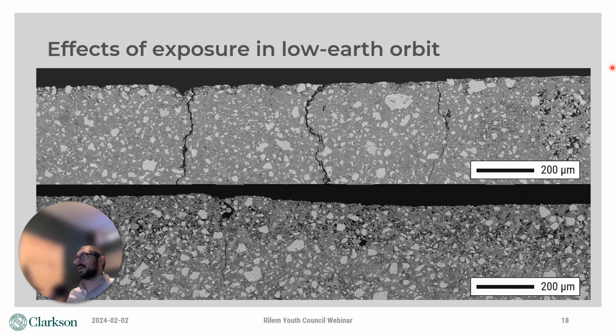They flew the samples back to Earth and we cut them perpendicular to the exposed surface to look at their microstructures. Here you see 2 of those samples, where this black region at the top represents the exposed surface. The top sample experienced significant surface cracking, probably due to thermal cycling. The bottom sample experienced a lot less cracking. The difference here is that the bottom sample was fiber reinforced and the top sample was not. You can see some of the fibers right here.